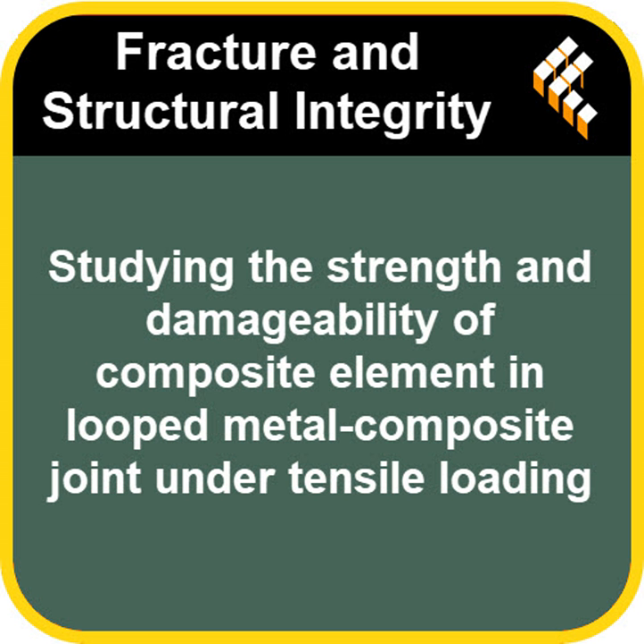Was anything else happening down there? What about the binder, the epoxy? Yeah, something else was seen. The B-scan images, these give you a cross-sectional view, like slicing through it. Right, like looking at the layers sideways. Exactly. Those showed that as the load increased, the surface of the specimen in the contact zone became rougher. And this was due to the extrusion of the polymer binder.